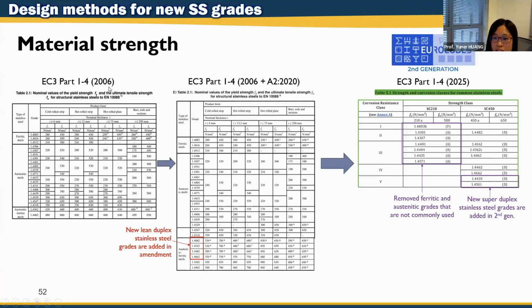So Eurocode 3 Part 1.4 has an older version of 2006. In this version, there are only ferritic, austenitic and duplex stainless steels. There is no lean duplex stainless steel at all. In 2020, there is an amendment that new lean duplex stainless steel grades are added. So in the amendment, Eurocode did not add any other grade. They only added lean duplex stainless steel grades because in Europe, they see the potential of lean duplex in structural application. That is why they added more lean duplex stainless steel grades.